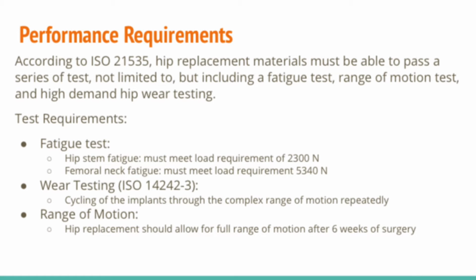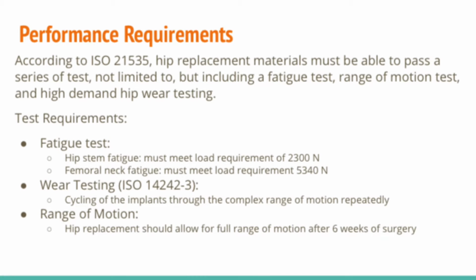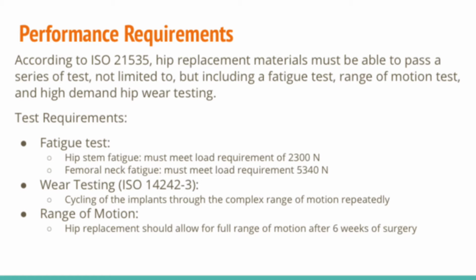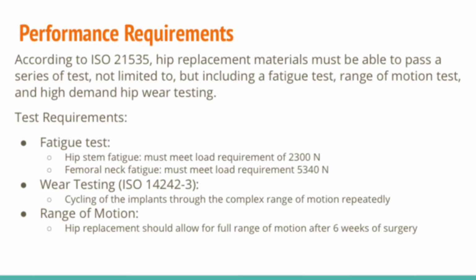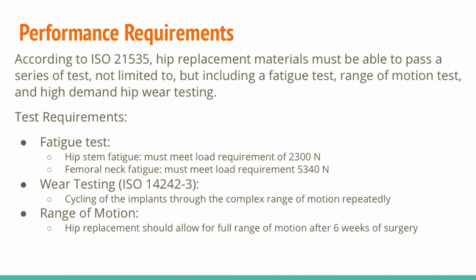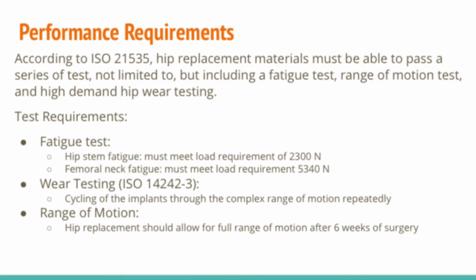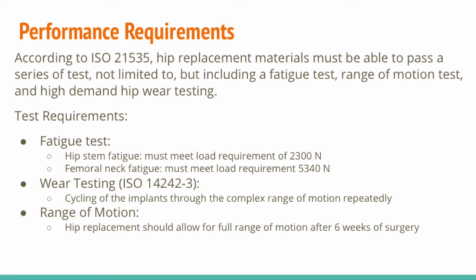For the hip stem fatigue part, the hip stem part of the replacement joint must meet the load requirement of 2,300 newtons. For the femoral neck fatigue part, the femoral neck part of the joint replacement must meet the load requirement of 5,340 newtons. For wear testing, which refers to ISO 14242-3, the implant must be cycled through the complex range of motion repeatedly to simulate what will occur once the implant is surgically inputted. And finally, for range of motion, the hip replacement should be made so that there is a full range of motion within this surgically inputted joint after 6 weeks of rehab.